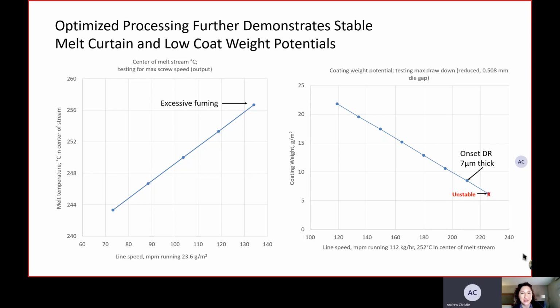So we backed it back down to 112 kilograms per hour and a melt temperature of 252, and said we don't want to go any faster than that to maintain the integrity of the polymer. So we set our extruder output at 112 kilograms per hour.